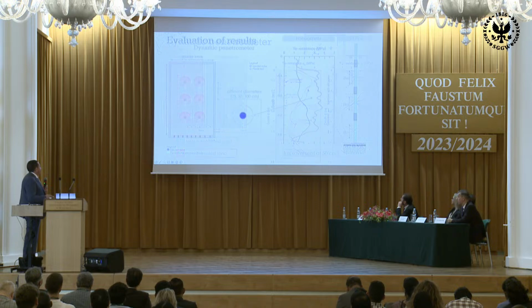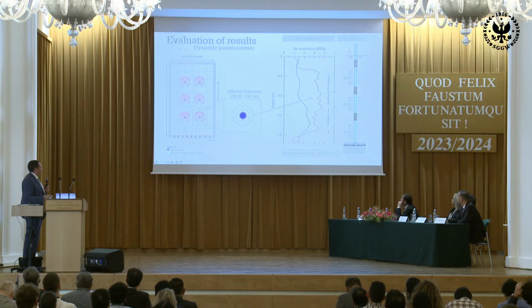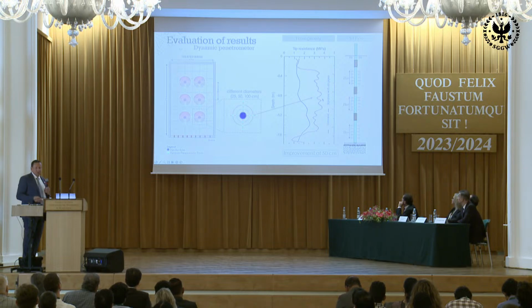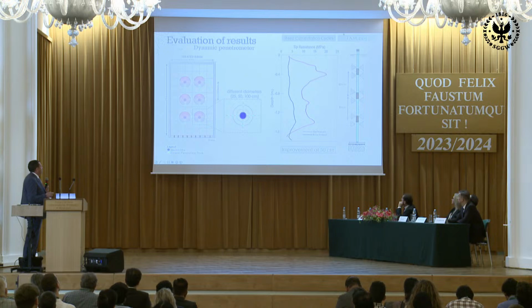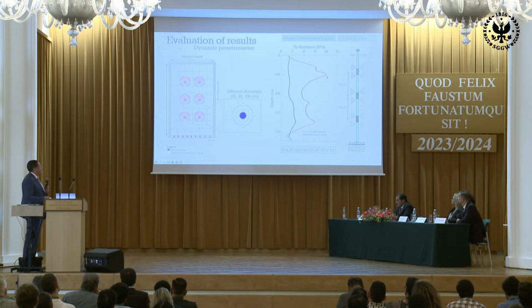As you can see, we are moving from almost 0.5, if not 0, megapascal to 3 megapascal of improvement in the ground. Then we look at 2 different ways to ensure homogeneity, for instance, by using slip pipe systems. And you can see here we can go up to almost 4 megapascal. And we can go even further, for instance, if we use a tube manchette system after different recycling, I think in this case it was 3 times injection in the ground, we can reach almost 20 megapascal of tip resistance.